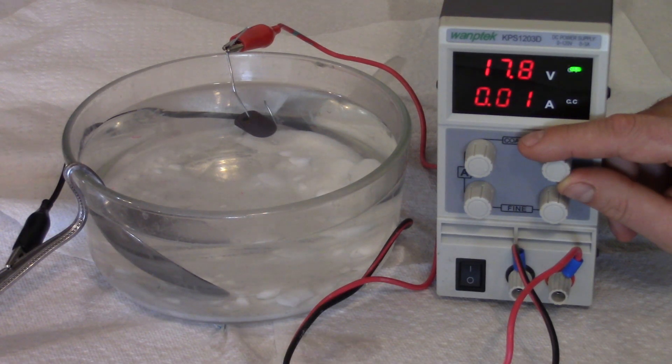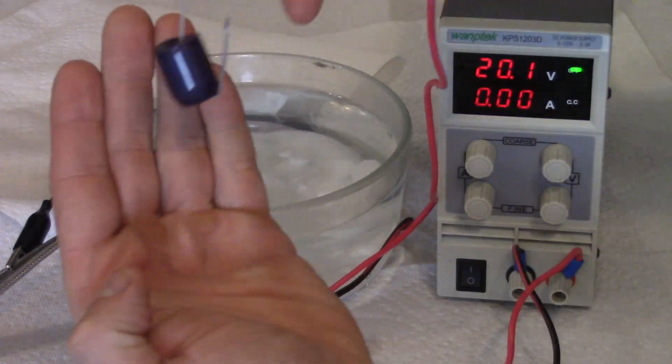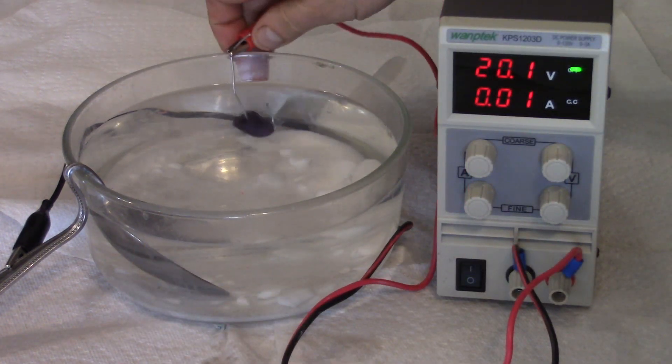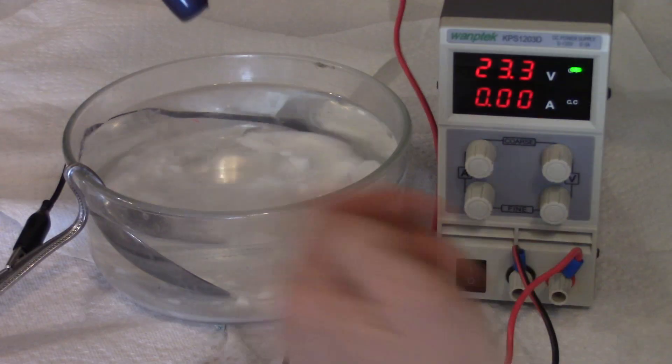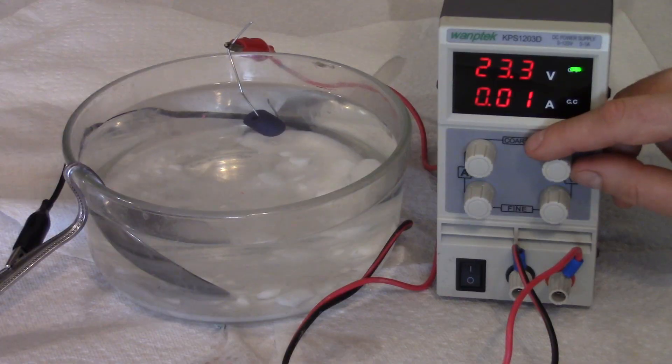So slowly go up, as we start to get into the 20s these purples will turn towards blues. And I'm trying to go real slow, this thing is very sensitive. At 20 we get a nice purple, it really comes out a little better, not quite as dark. Nice purple color there.